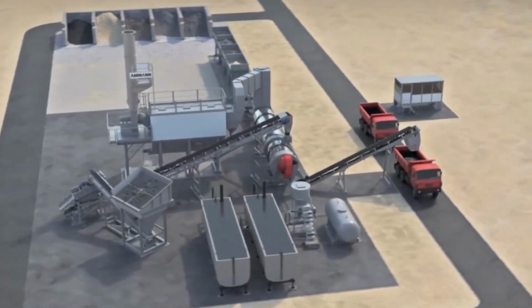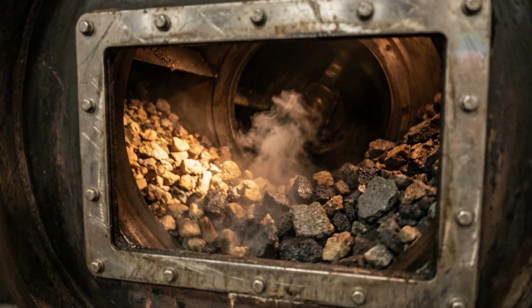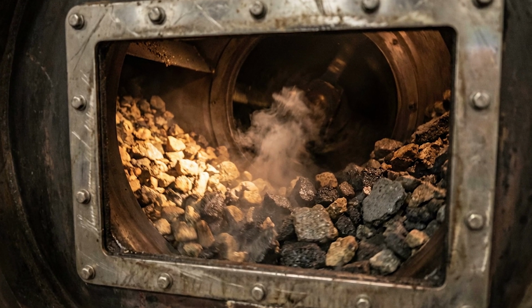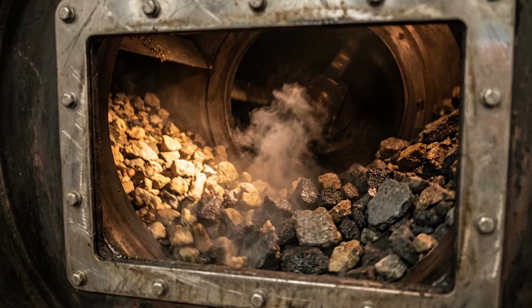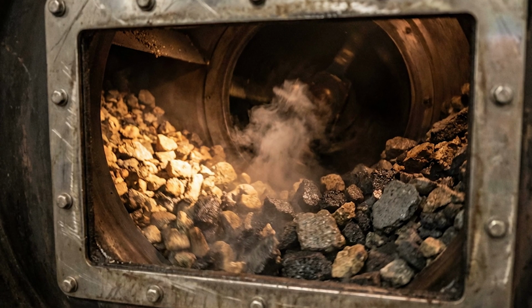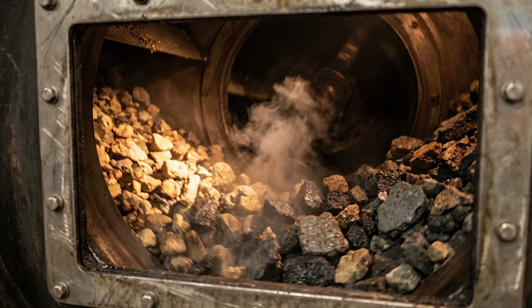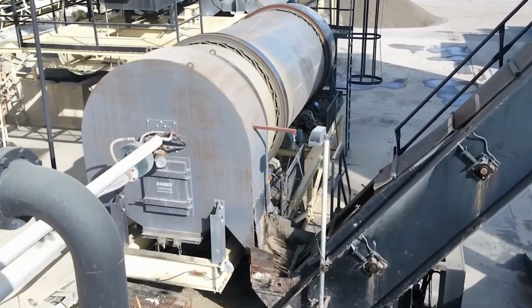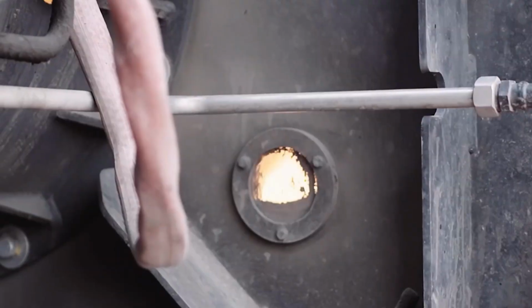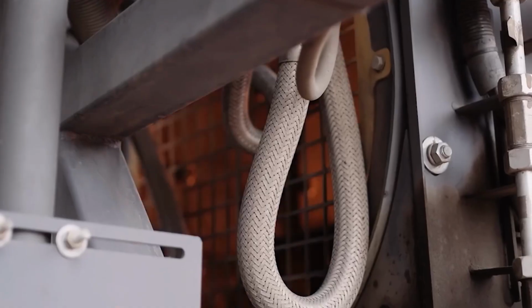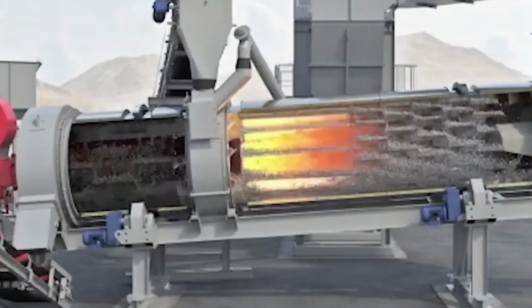It never sees the fire. Conductive transfer. As the drum rotates, the superheated virgin rocks mix with the cold, wet RAP. The heat transfers via conduction, rock-to-rock contact. This creates a steam flash that dries the RAP and melts the old binder gently, keeping it below the oxidation threshold. So far, we have stabilized the aggregate size and neutralized the moisture. Now, we must repair the chemistry.